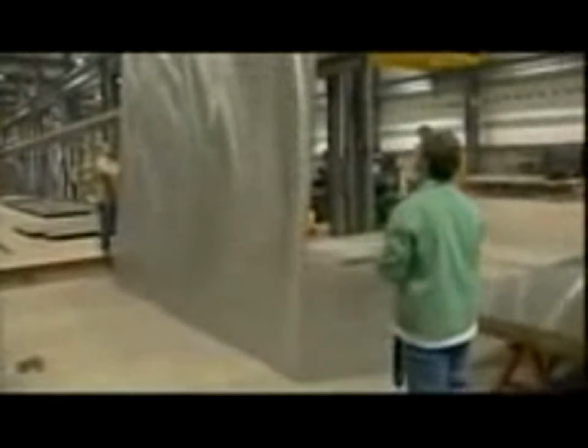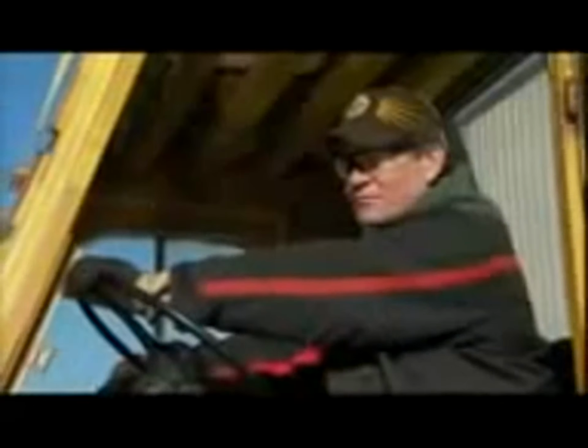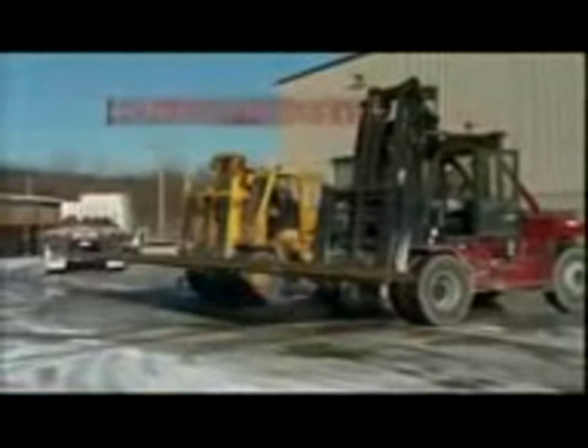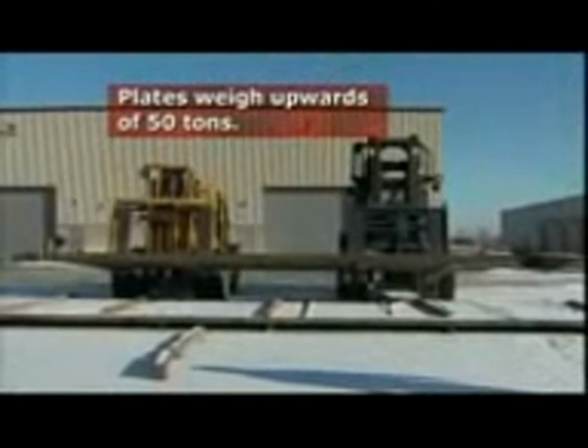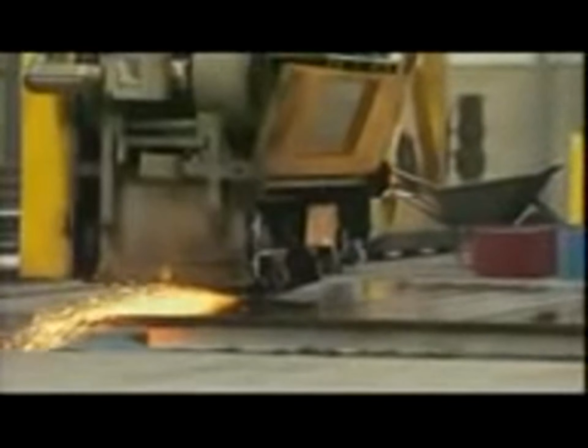Today, Dynamic Materials Corporation is a world leader in explosion welding technology. Here, the decades-old discoveries from the battlefield have been refined into an exacting science. The explosion welding process begins as soon as the two metal plates arrive at DMC's main plant, outside of Pittsburgh, Pennsylvania. To maximize the welding force of the explosion, the surfaces of each plate are ground as uniformly flat as possible, a process that also removes any rust, oxides, and other surface flaws.